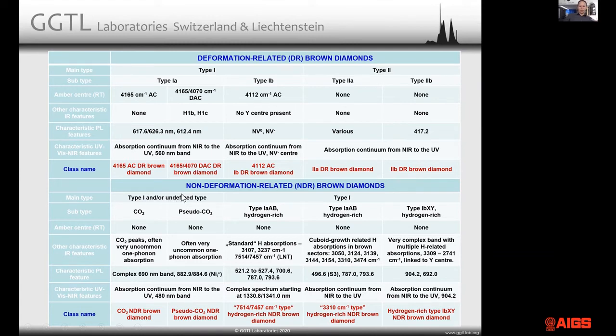The non-deformation related diamonds are classified by type 1 and/or undefined type, because in CO2/pseudo CO2 diamonds, sometimes you have cases where there is no nitrogen related absorption distinguishable. So you cannot actually define what type they are. And then the other types are the hydrogen-rich stones that are type 1AB, which are subdivided into the cuboid octahedral and the standard ones with the 1330.8, 1341 nanometer bands, and the hydrogen-rich type 1B diamonds.